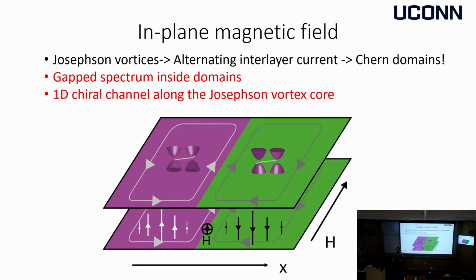Right, I see. So one way to avoid some of the questions I just got is to avoid current altogether. It's possible to do this by applying an in-plane magnetic field in this system. Because I have two layers of a superconductor, I can think about this as a Josephson junction. What is known about Josephson junctions is that if you apply an in-plane field, you actually generate vortices, like in any superconductor, but these vortices are different from your usual Abrikosov ones in the sense that their core is between the two planes. So you're not suppressing the magnitude of the order parameter, you're just winding its phase. And what you expect then, like from any vortex, is current going between the two planes, up here, down here. And as I just told you, applying current between the two planes should open a gap.